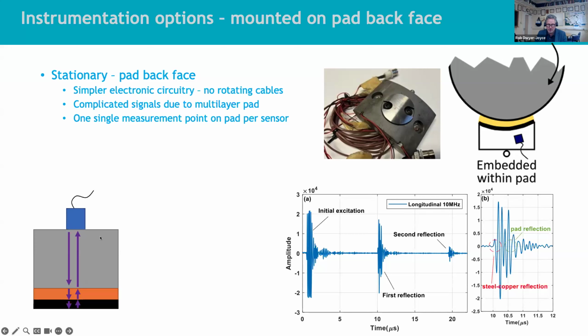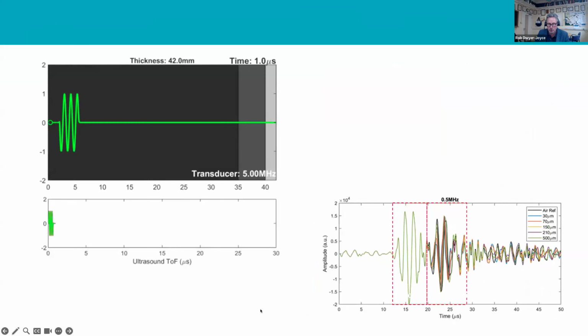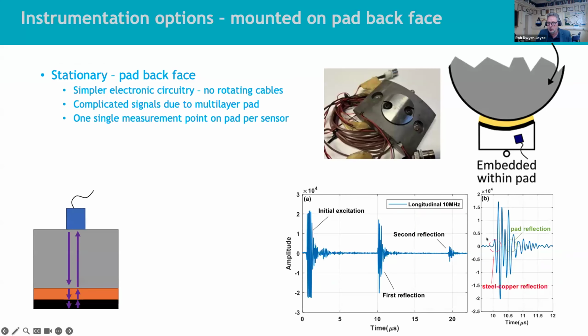The problem is these pads, as Emily pointed out, are likely to have a facing material, a polymer. If it was metal facing like white metal, it wouldn't be any problem. But these polymers and then an interlayer, they have their multiple reflections. They're going to reflect back from here, reflect back from here, and reflect back from here. So the signals start to get a bit messy. So you don't get a nice clear reflection. You get a reflection which contains lots of other information as well.